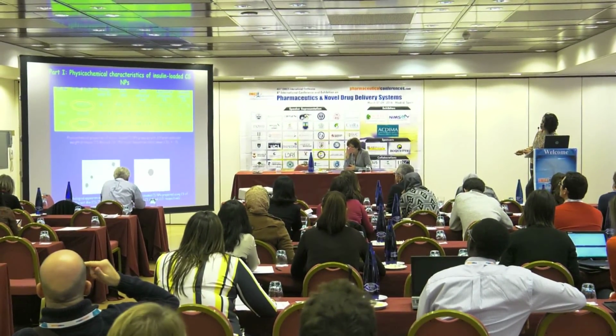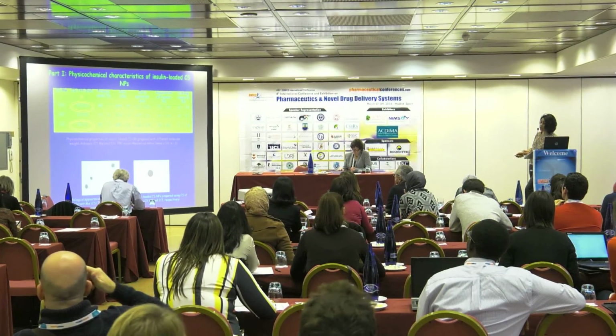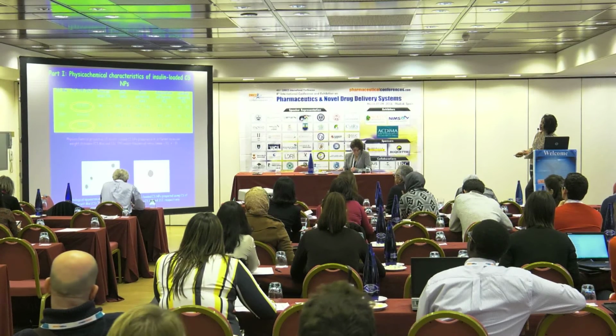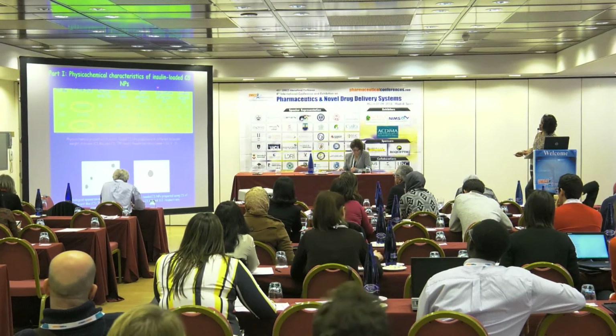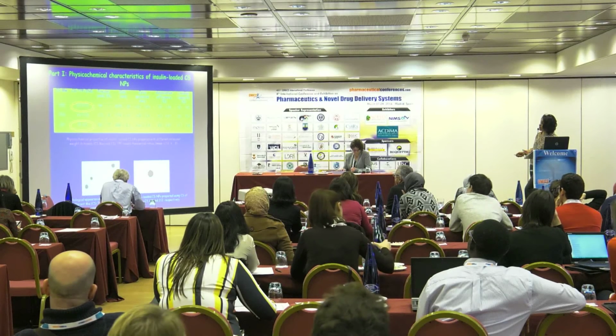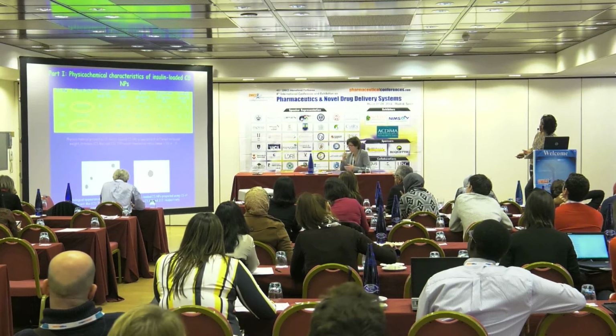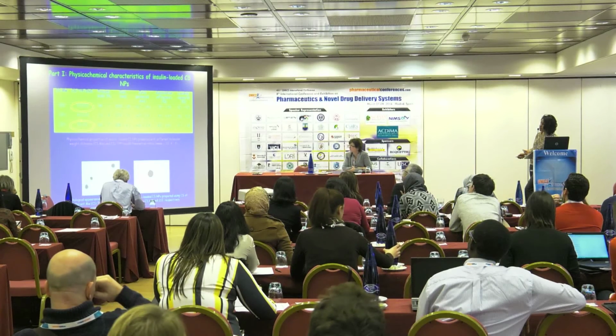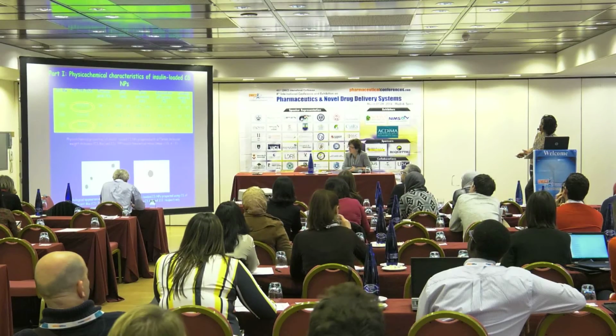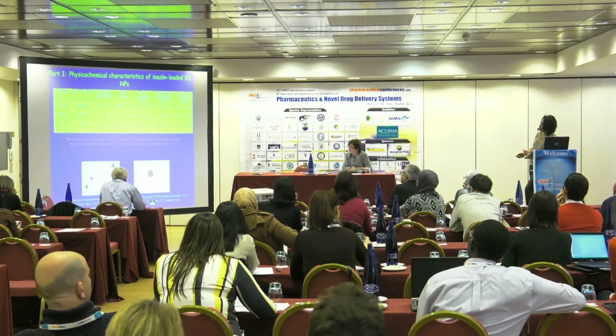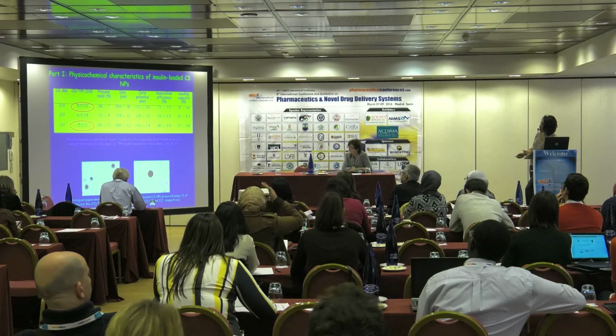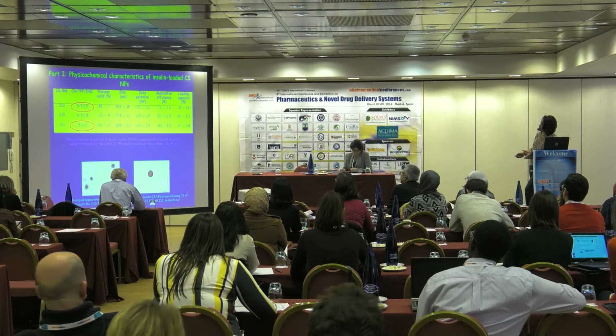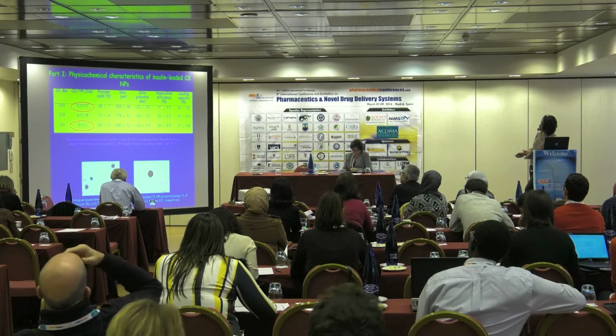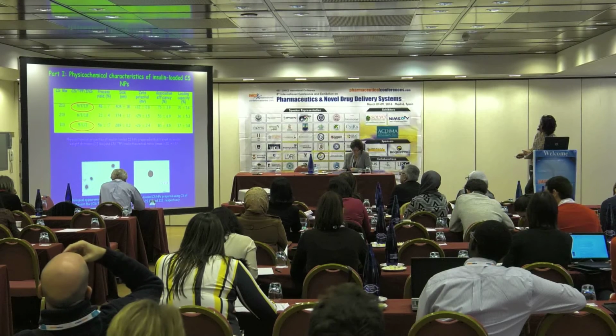We obtained many formulations, and finally screened them based on process yield, size, zeta potential, and association efficiency of the protein or loading capacity. We selected the two most important formulations to proceed with, which achieved process yield between 48 to 56%, nanometric size between 289 to 404 nm, with positive zeta potentials ranging from 26 to 32, and high association efficiency of the protein ranging from 75 to 83%.